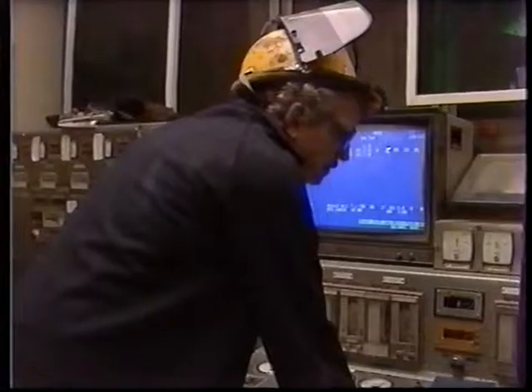Once the molten metal is charged into the refractory lined vessel, the mixing and stirring begins, using critical combinations of oxygen, argon or nitrogen to increase the temperature, stir the molten metal, and at the same time reduce the carbon content.